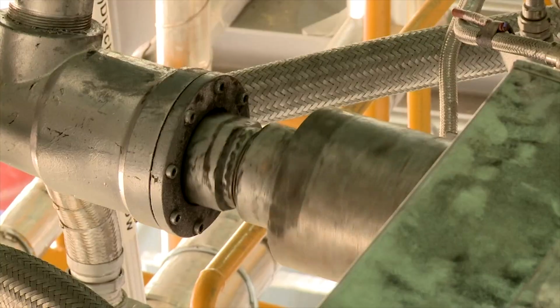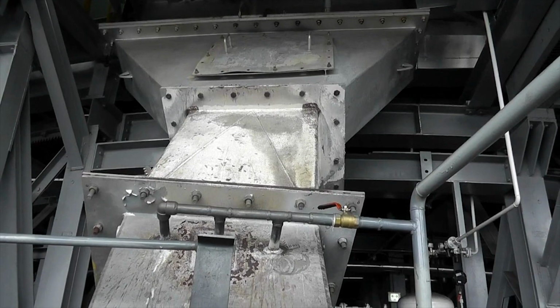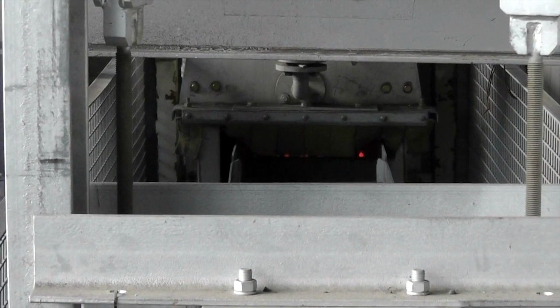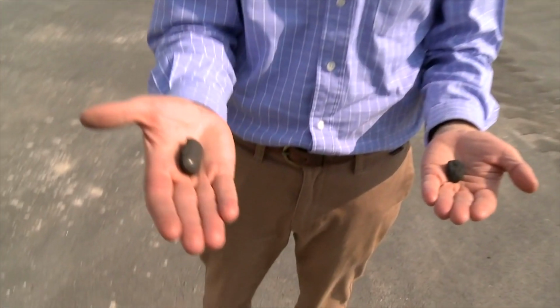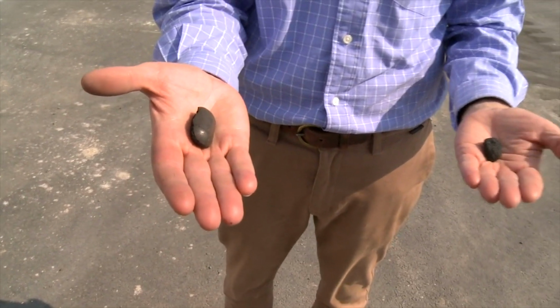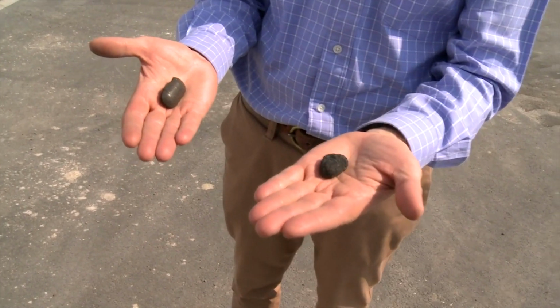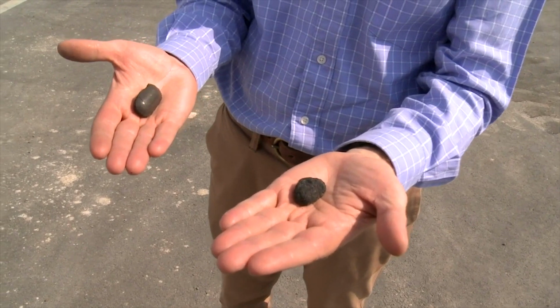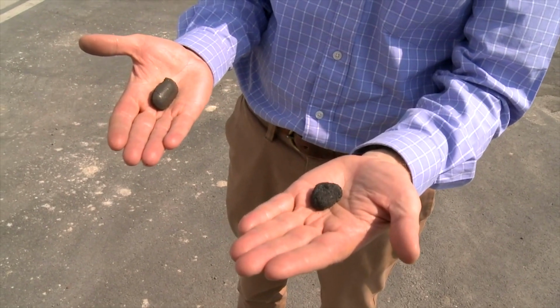Near the end of a full rotation, the briquettes encounter a large auger screw that sits just above the hearth and discharges them to a chute at the outer edge. Before we put the briquettes into the furnace, they look like this. By the time they've gone through the furnace, they come out looking like that. They've lost their zinc, lead and oxygen, and they're about 60% of the former size.